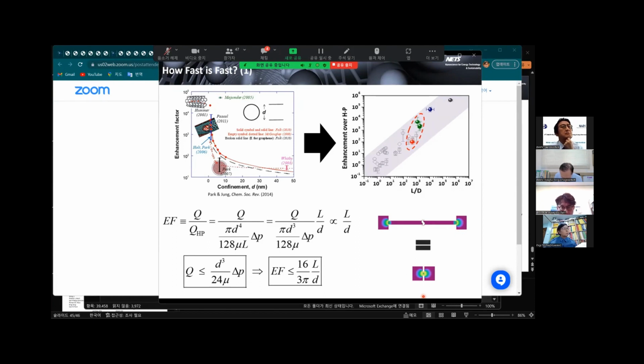We assume that the transport rate through carbon nanotube channels relies on the entrance and exit resistance, which is shown here, but not on the channel resistance, and then set the maximum enhancement factor by substituting Q with Sampson's formula to result in the maximum value of the enhancement factor.